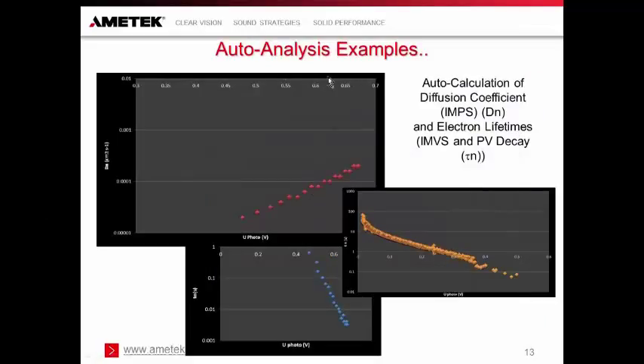So here's some examples from the auto analysis, including diffusion coefficient as a function of photovoltage, and notice how the diffusion coefficient decreases as we decrease the voltage. The electron lifetime as a function of voltage, and again this is the electron lifetime as a function of voltage using the PV decay technique. And these are invaluable tools because they help the end user understand how the chemistry and physics of the cell are affecting things like the diffusion coefficient and the electron lifetime.